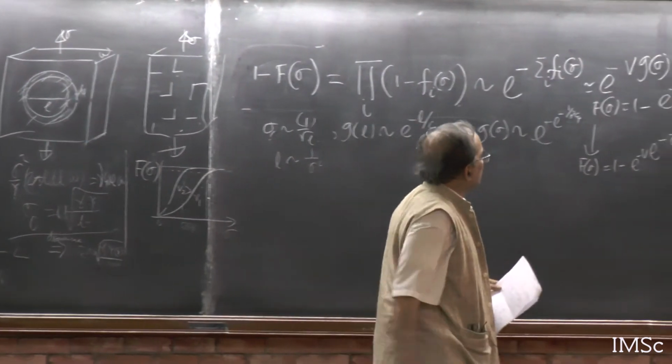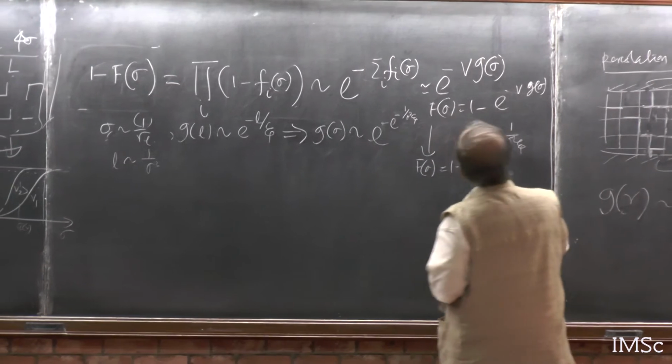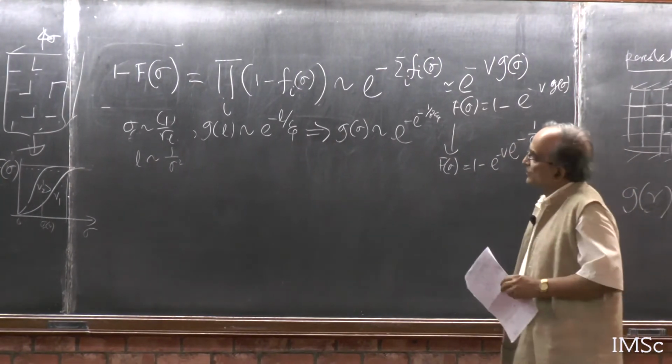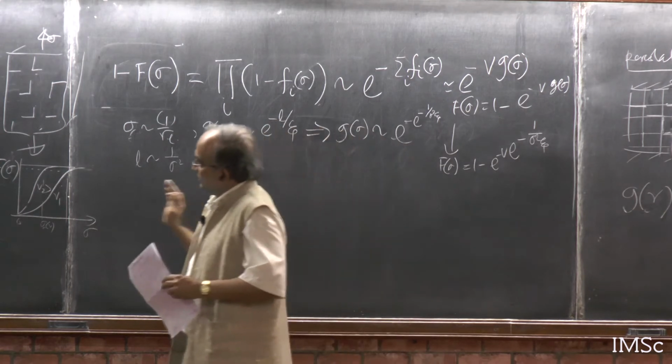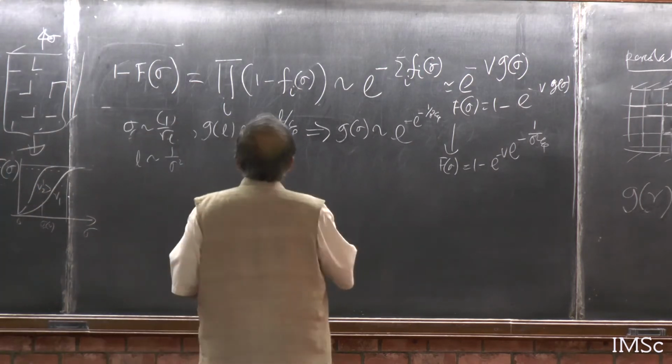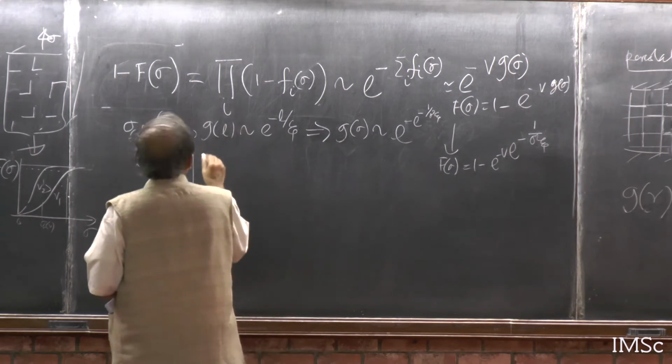But put some finite value, 90% chance that it will fail, and it will give you, for any v, a sigma c which will decrease with volume in a way that is given by this form. This form is one of the important forms for all engineering mechanics.